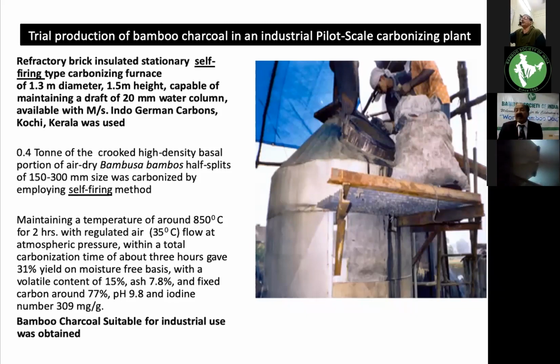We employed 0.4 ton of bamboo in this small kiln, in the form of half splits, and the self-firing method was employed because the kiln is meant for that type of thing. Maintaining a temperature of about 850 degrees centigrade for 2 hours with regulated air at about 35 degrees centigrade at atmospheric pressure, within a carbonization time of about 3 hours, gave 31% yield on moisture-free basis with a volatile content of 15%, ash of 7.8%, and fixed carbon content of about 77%, with a pH of 9.8 and iodine value of 309 milligram per gram. So this indicates that bamboo charcoal suitable for industrial use can be obtained even by using a small kiln.